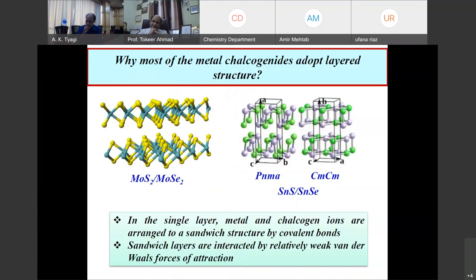I move forward. Most of the metal chalcogenides adopt layered structure. Have you wondered why? In research, you must ask questions to yourself. Why is it that metal oxides predominantly adopt close packed structure, and so do metal fluorides, but sulfides and selenides and tellurides adopt layered structure? Again, the reason lies with high polarizability of anion. When you have highly polarizable anions like sulfur, selenium, etc., you do not have a direct bond along the c-axis. You make a sandwich type structure.